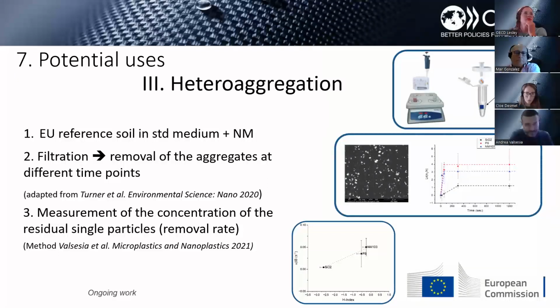The first results here are promising, as you can see from the curve at the bottom of the slide, with a trend appearing between the hydrophobicity index and the attachment efficiency. But again, this study should go much further with a larger batch of nanomaterial tested, and we are planning a collaboration on this topic to really study the potential correlation.